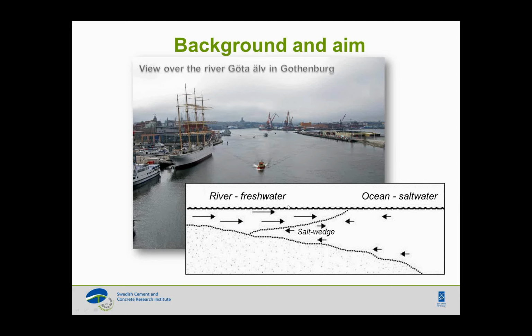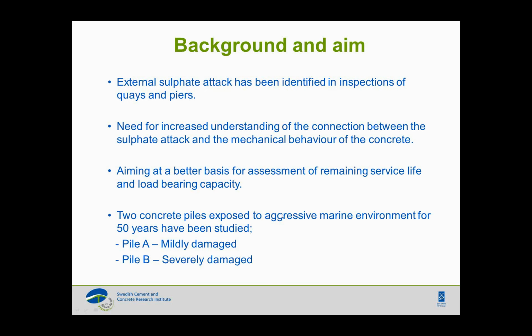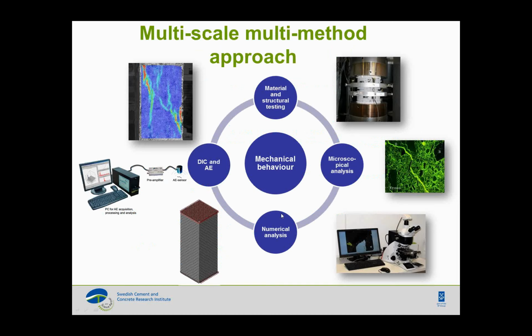One of them, which we call pile A, had mild damage on it. It was no severe damage, but pile B was severely damaged due to sulphate attack. We started with this multi-scale, multi-method approach. So we used material and structural testing in terms of quantifying the compressive strengths, or the behavior of concrete in compression and in tension. We also did full-scale tests on some of the piles.